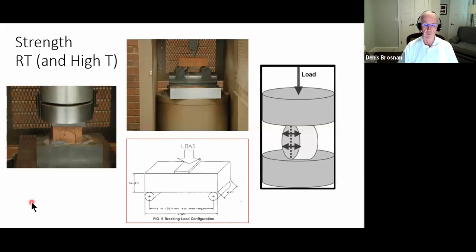Now I'm going to make just a few comments about strength, not very many. Of course, we have compressive strength. There's a brick being tested for its compressive strength. It actually breaks by tensile splitting. If you look very carefully, you'll see that during the failure of the ceramic, we get vertical cracks in it, and it's trying to form a pancake or rounded shape on the ends. The rounded ends break off in the test, and we get these vertical cracks. Compressive strength is important in bearing strength in a ceramic.